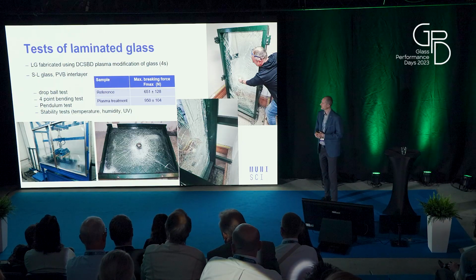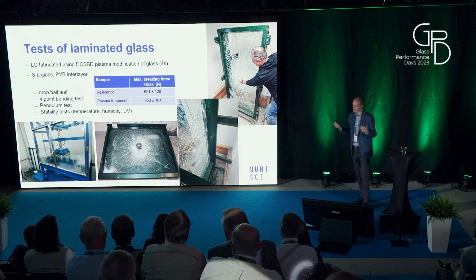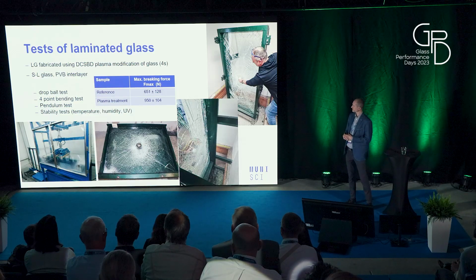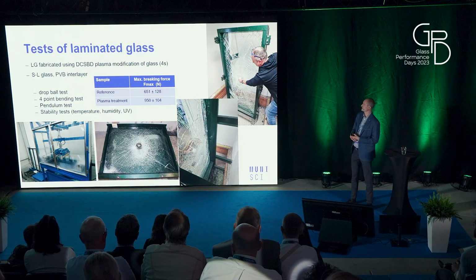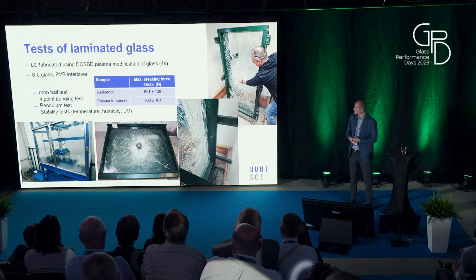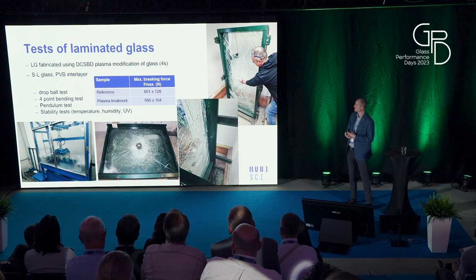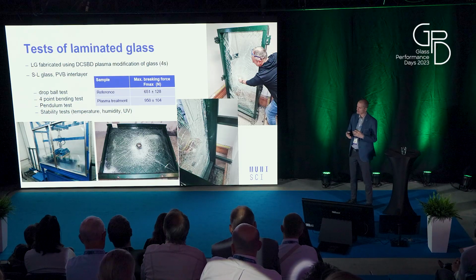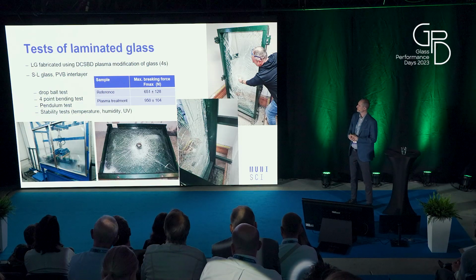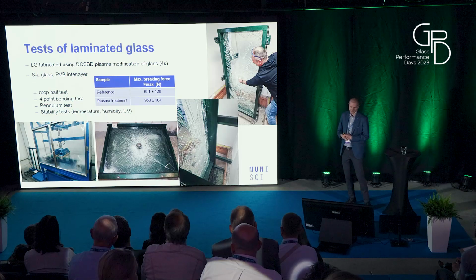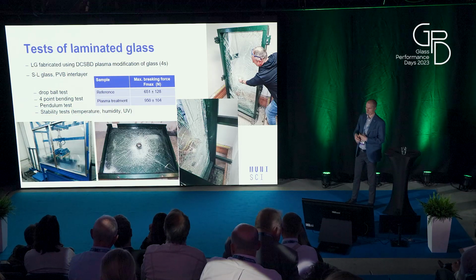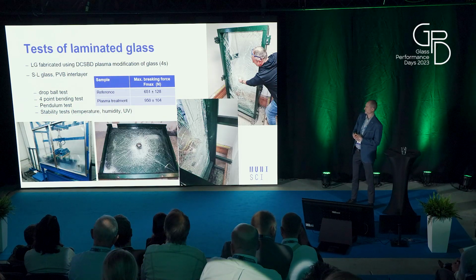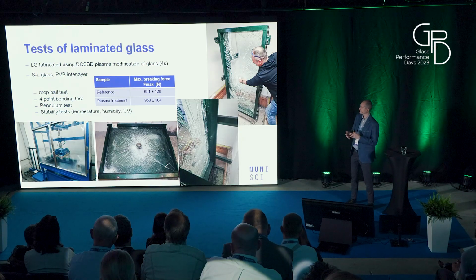We created laminated glass using the standard wet-cleaned glass, and we measured the breaking force of this sample at around 650 newtons. For laminated glass created using the plasma-treated glass, we measured a breaking force of 950 newtons, which is an improvement of roughly 50%.